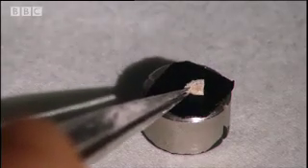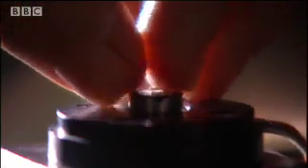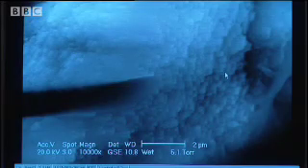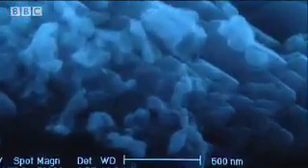This may look like a Martian worm, but Ken Nielsen has shown how deceptive appearances can be at this minute scale. The pictures of the Allan Hills meteorite were taken using an electron microscope, and to get the best images, the rock sample was coated with an extremely thin layer of gold. Nielsen's team have been looking at rocks with a new kind of electron microscope — one that can work without the gold coating. His uncoated rocks look jagged and crystalline at high magnification. But add the gold coating and tiny blobs appear, which are about the same size as the famous Martian worm. The edges can be rounded off with the gold, and even an expert could be fooled.